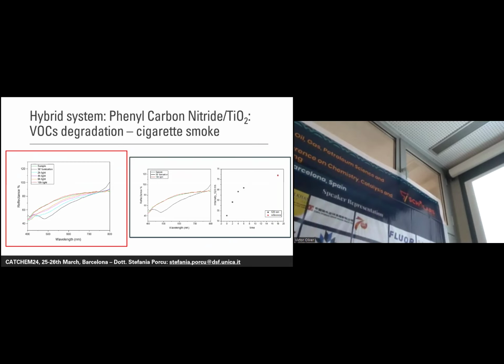What you can see from the reflectance measurement shown in this slide is that when you started the experiment, the reflectance spectrum is the one in green, called sample in this graph. After the fumigation, the smoke process, you can see that the reflectance spectra changed a lot because of the presence of the carbonaceous residuals from smoke. And then we started to shine light on our film. What happened is that the reflectance measurement changed during the time until it returned as it was before this smoke process, meaning that all the carbonaceous residuals have been degraded.